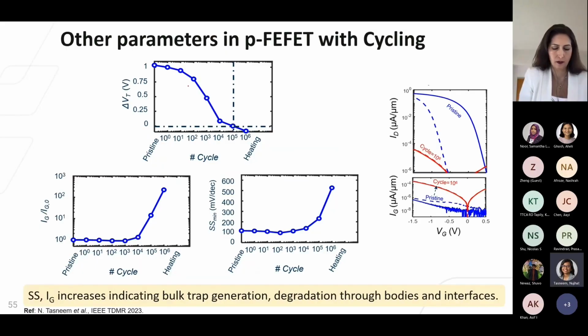So we also evaluated some other parameters and observed their evolution with fatigue cycling. For example, the first figure here shows that memory window decreases with fatigue cycling, which is expected. And this figure shows that the gate leakage and the subthreshold swing increase as we keep on cycling the device, indicating bulk trap generation and interface degradation.